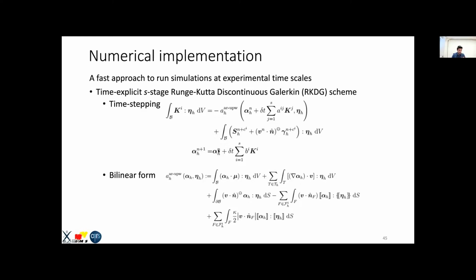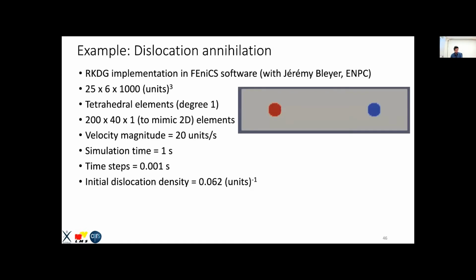It took me 4 months to get to this point, and I'm quite happy. This is a very nasty formulation, but we got here and we did an annihilation simulation. So these are the parameters of this simulation. The key point here is that the simulation time was 1 second in 1,000 time steps of 10^-3 seconds. This is the experimental point of view that I want to give you: this is what we were targeting, to do it at experimental time scales.